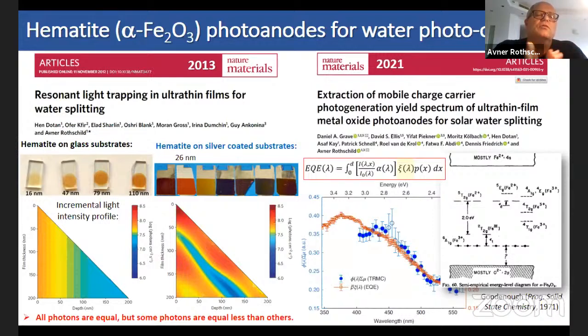So there is a very short length where you can separate and collect them before they recombine. This requires nanostructure devices in order to reduce the recombination. And our approach to this problem was using ultra-thin films. And when I say ultra-thin films, it's films on the order of 20 nanometers. That's the distance where you can still have high efficiency of electron-hole separation without recombination. As you can see, in the normal design, where you put these layers on a transparent substrate, they absorb very little light, okay?